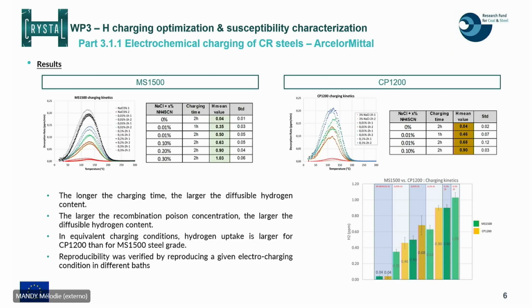So here you can see a brief insight of the results. You have the results for the MS 1500 on the left, for the CP 1200 on the right side. What you see is the desorption rate as a function of the desorption temperature for the different conditions. And you see in the table a rapid summary of the hydrogen amounts obtained in the different conditions, with various amounts of ammonium thiocyanate and various charging times.